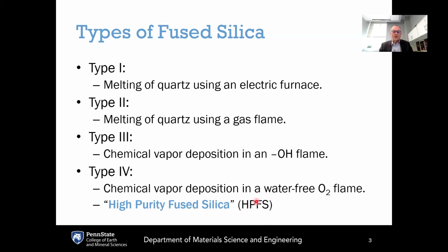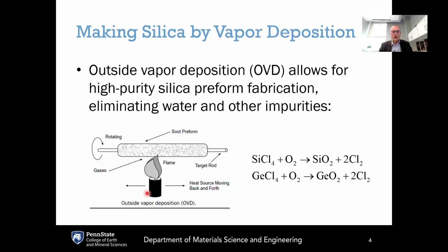So if you hear this acronym HPFS, this is implying type 4 fused silica, which is made via chemical vapor deposition in a water-free oxygen flame. So this is all done in a hood under a controlled atmosphere to make sure that the system is free of water. To give you an idea of how this works for making a fiber optic preform,